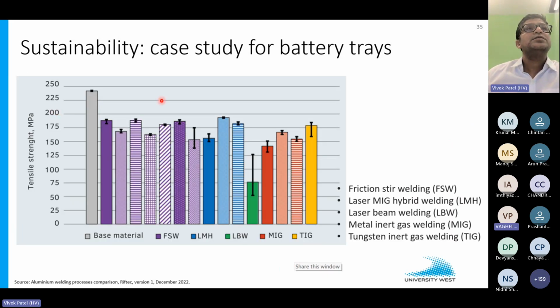So you can see some results. This is a base material of 6000 aluminum in T6 condition. And if we see the graph of tensile strength, you can see that friction stir welding is matching some hybrid welding, and this laser MIG hybrid welding. So the other processes also show quite decent tensile strength.